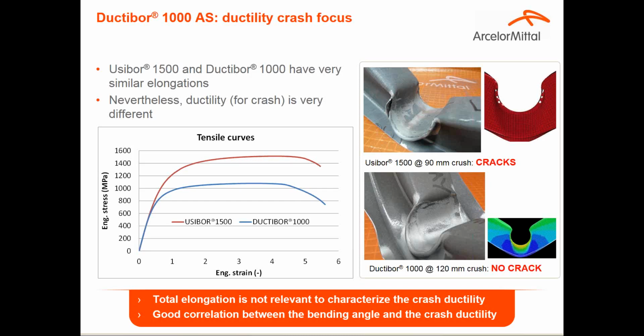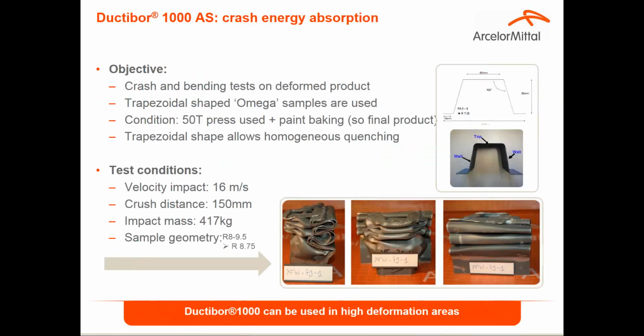And then looking again in more detail at how we study crash energy absorption, we see a simple test, an axial test, that is used mainly to do two things. The first is to develop and provide to the customer all the information needed to simulate the application and to have a good correlation between simulation and the real test. And second, it also shows that Ductibor 1000 can be well applied in applications such as front rails, rear rails, or members, cross members.